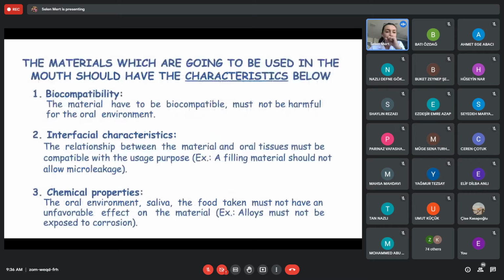But beryllium is documented as a carcinogen, although there is no study that shows beryllium leads to cancer in humans. However, beryllium may lead to berylliosis disease, which affects the lungs as a chronic inflammatory condition. Especially technicians or prosthodontists may have berylliosis due to beryllium in nickel-chrome alloys. If we inhale beryllium dust or fume during casting or grinding and polishing, we may catch the disease of berylliosis.